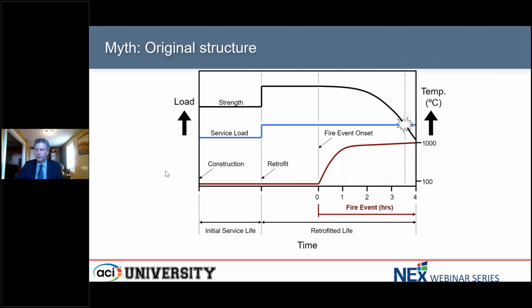And this other schematic, we actually give some credit to the ACI people at Concrete International for thinking about trying to describe some of the work that we've done. So you build a structure and it has a certain strength, and this is a corresponding service load. Then you retrofit it at some point, which increases both its strength and the service load. Then at some time later, you have a fire event. And of course, this is an expanded time scale because this is 4 hours and this is years perhaps. This red line represents the time temperature curve. And this black line is what happens to the strength during the fire if you have insulation present. So you can see that it slowly degrades and then finally you get some failure at this point.